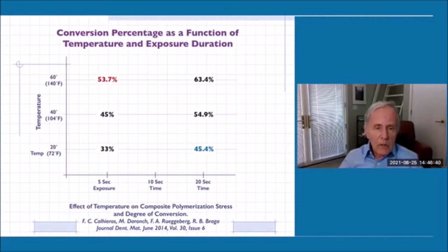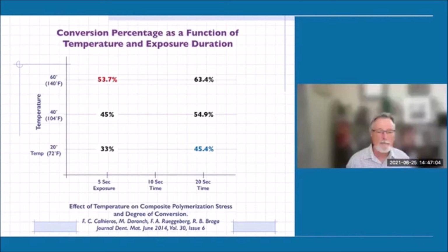So what we noticed is that the warm material had a 53.7% conversion, and the material that wasn't warm had a 45.4% conversion. So in curing less time, we actually got more polymerization. That's really interesting, and it's important. Well, you might say, if I just cure longer, I can get higher conversion, and that's true. But something else is happening, as we'll see in the next slide.